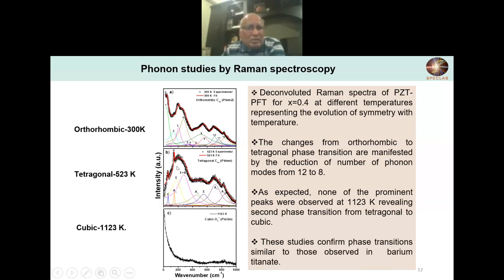This is what was expected in the case of a phase transition, or two structural phases. In the cubic phase, since it is a centrosymmetric material, there is no more Raman scattering occurring, so you can see there are no Raman features. This also supports our theory about the phase transitions in this material.